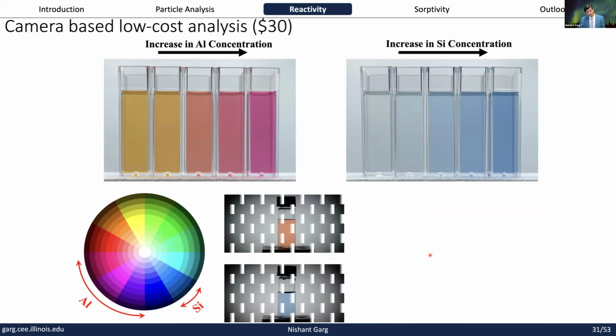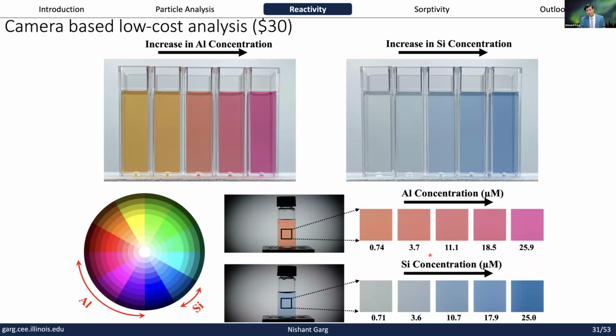Just double clicking on this low-cost camera-based analysis, one thing you have to be careful about is that you build a calibration curve under controlled conditions. Once you do that, you can measure concentration at the micromolar level, which is on the ppb level. You can now measure aluminum and silicon with just a $30 camera, which I think could be quite useful in places where you don't have access to high-end instrumentation.